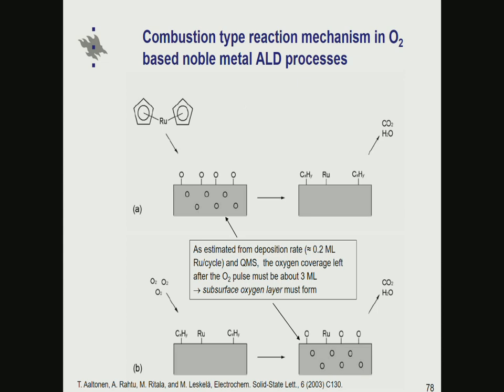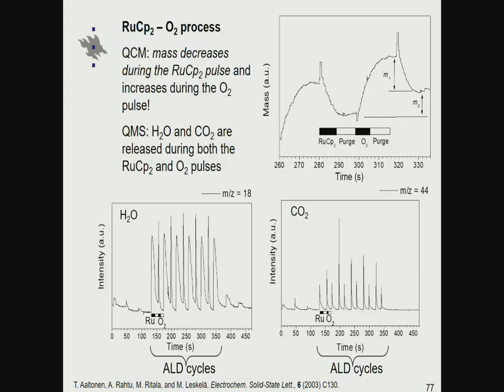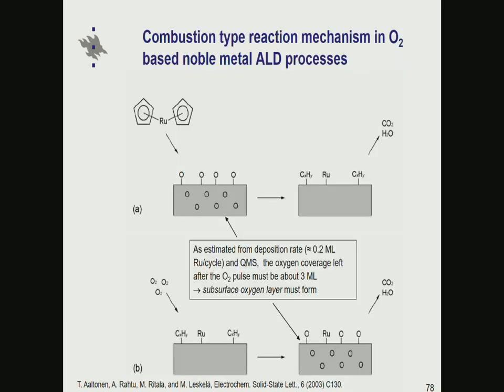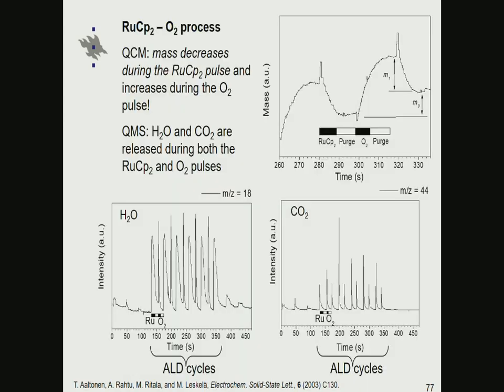And now, even if we are adding ruthenium atoms during this step, we are removing so much of this atomic oxygen that the net effect on the film mass is actually a decrease. So more oxygen atoms are being removed in mass than what is being added on top, and vice versa during the next pulse. So even if hydrocarbon ligands are indeed removed here, one adds so much oxygen that one sees the mass increase during this pulse here.